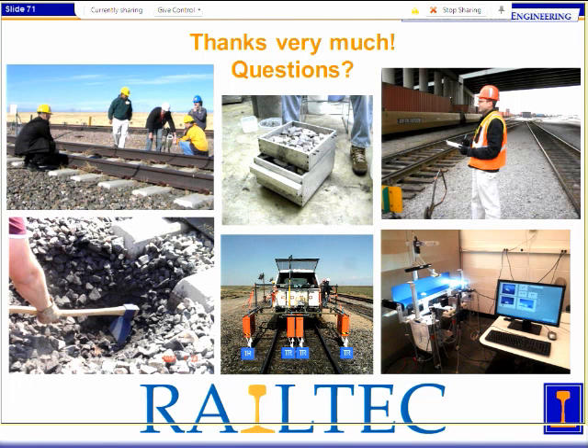Now for correlation, we have seen it for some of the ones that matter the most, namely especially ballast 13, with the exception of measuring durability. Ballast 13 we observed had the lowest strength, had a horrible flat and elongated ratio, and is not very good. Now, as I mentioned earlier, LAA has some notable issues that have been known about for quite a while with regards to predicting performance, and that can also be seen in the results. From a pure durability standpoint, it doesn't do too bad.